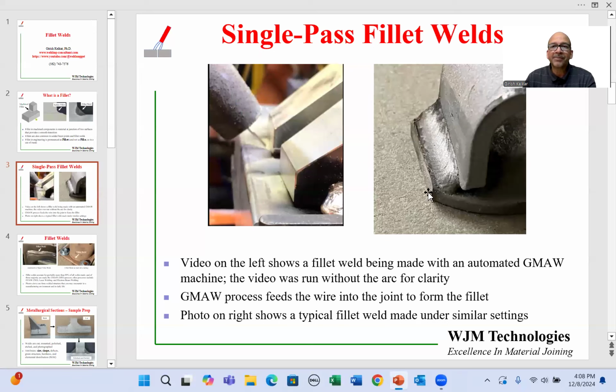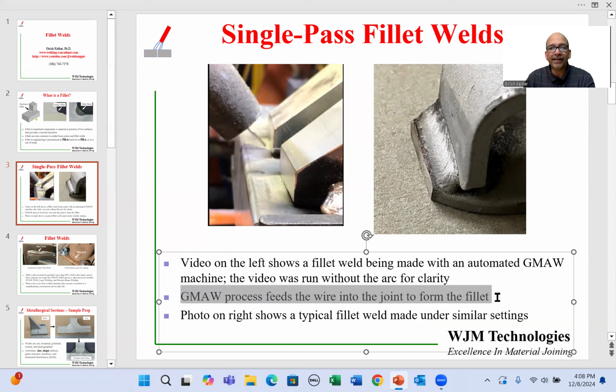A weld made under similar circumstances is shown on the right-hand side. This is not exactly the same components, but made under similar circumstances, and you can see a single-pass fillet weld from start to finish. In this case, we are talking about GMAW, gas metal arc welding process, which feeds the wire into the fillet. So you are actually adding wire to create that fillet.